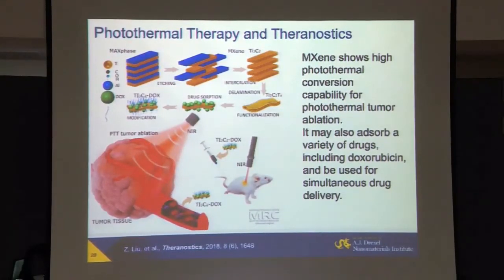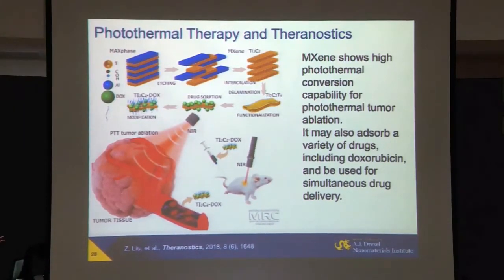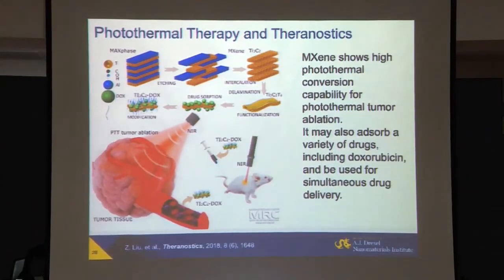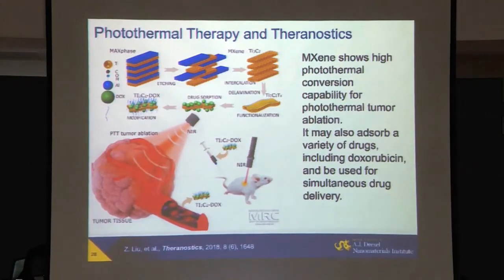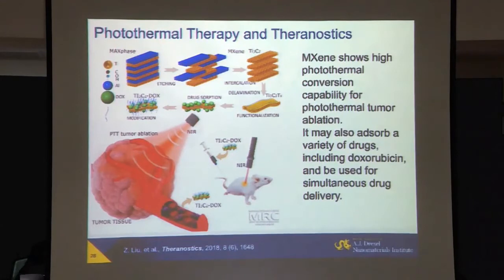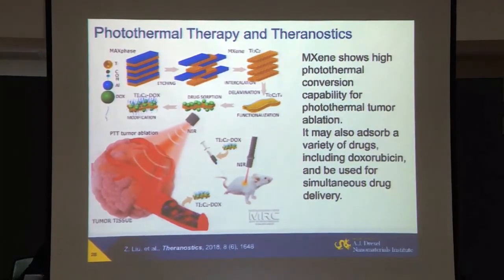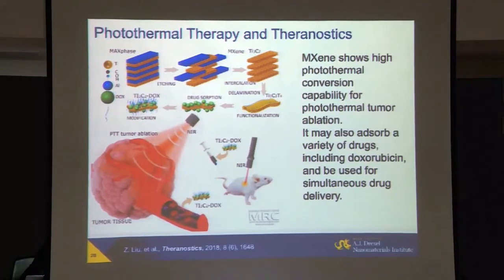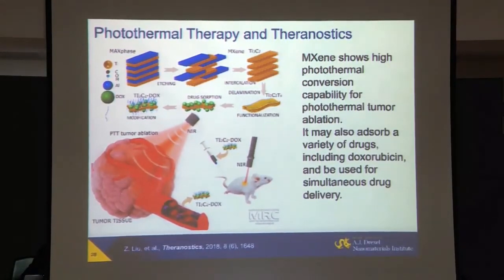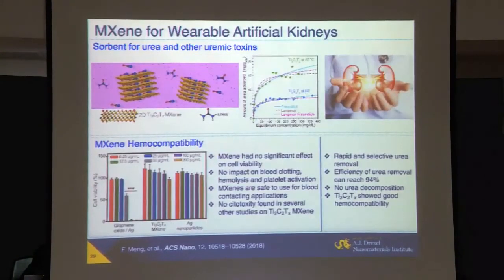I mentioned just a couple of minutes ago that many MXenes have plasmon resonance, so they basically absorb light and transform it into heat in the infrared range. So they can be used as light-to-heat transforming materials. And a big application I found is photothermal therapy, destroying cancer cells by illuminating them with red light because, for example, Ti3C2 has plasmon resonance at 780 nanometers. This is exactly positioned for a red diode laser. So it's a very, very common one, and it can go much, much deeper into tissue compared to visible light, which had to be used, for example, with gold nanoparticles. Moreover, many MXenes have plasmon resonance much, much further into the infrared, so infrared radiation can be used to heat it here. Many other applications.